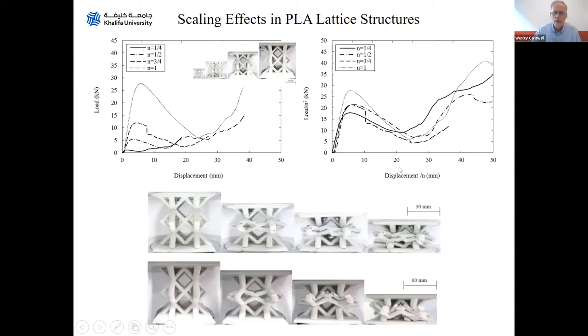And if we look at our scaled load displacement traces as well, there's a reasonably good degree of similarity, certainly in terms of failure modes, also in our load displacement traces. But again, there's a tendency for our larger samples to be stronger than our smaller scale samples. And once again, I think it's to do with the presence of these defects in our structures as we manufacture them. So I'm out of time.